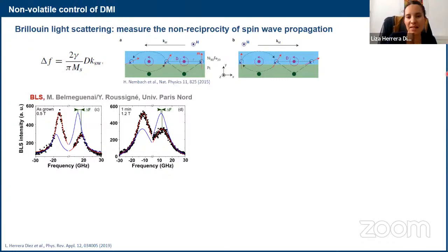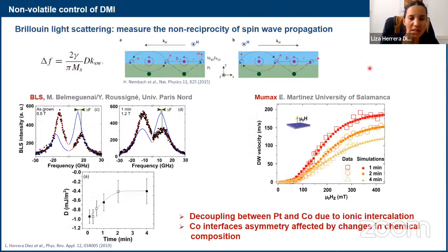And since DMI is setting one of the chirality, then the appearance of this frequency shift is a signature of DMI, and this is how we can measure it. So then we did measure it in this system, and we could see that as a function of the gating time, we could see a weakening of the DMI. So this is something that was also evidenced in the motion.